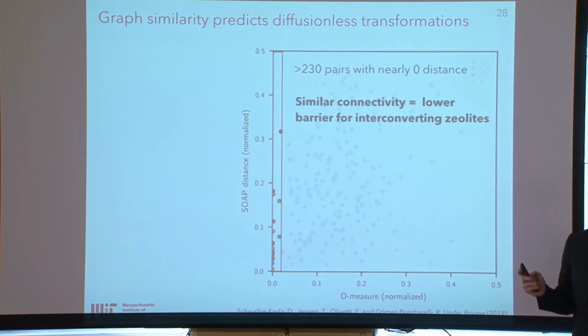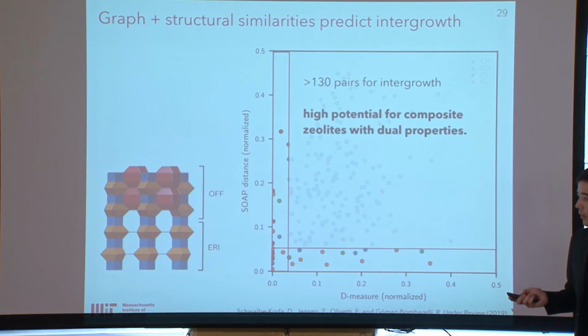So this may open a line of research to investigate whether we could achieve such zeolites with very custom silicon to aluminum ratio without the use of organic structure directing agents and so on. Finally, if we analyze not only the graph distance but also the structural distance, we see that all cases of zeolite intergrowth fall on these 2 regions of this plot. That is, zeolites that can be grown together, they either have very high graph similarity or very high structural similarity.